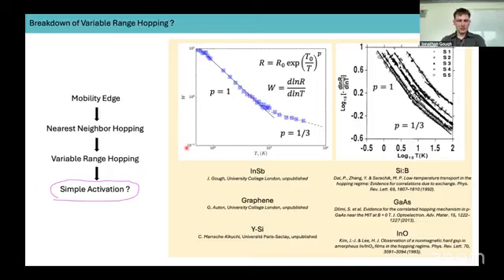You can see this transition to this regime in this W plot. These plots are slightly confusing. They're the derivative of the log resistance with respect to log temperature. But essentially all you need to know is the gradient of these plots gives this value p. At high temperatures, we observe p equals a third, so 2D variable range hopping. But then below a critical temperature, say around 10 Kelvin in this case, we observe p equals 1, hence simple activation. This has been observed in indium antimonide, the material that I'm going to talk about today.